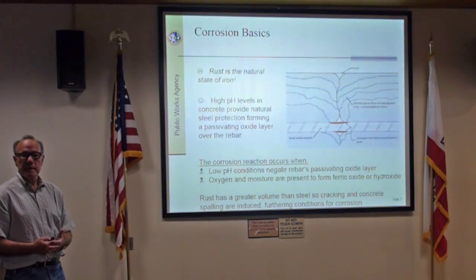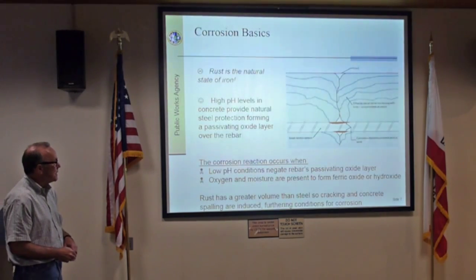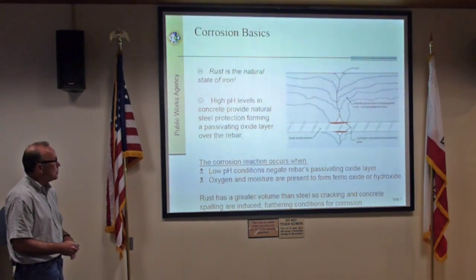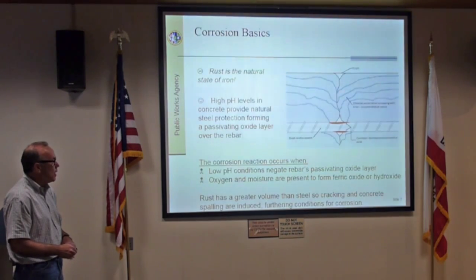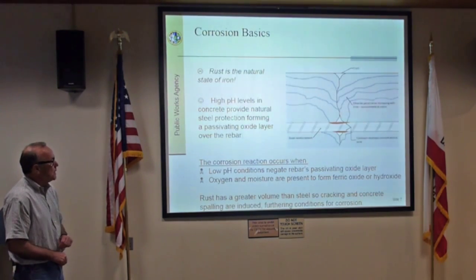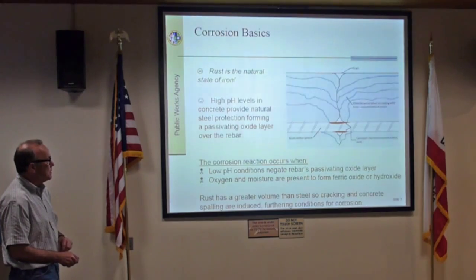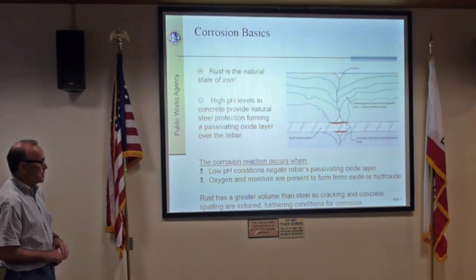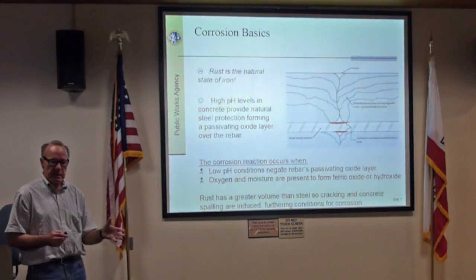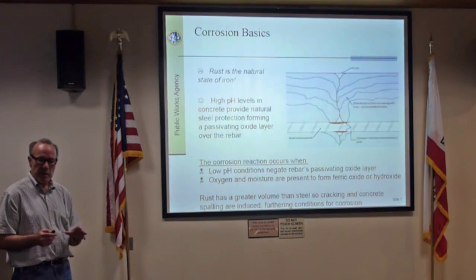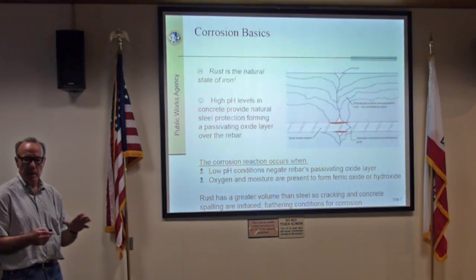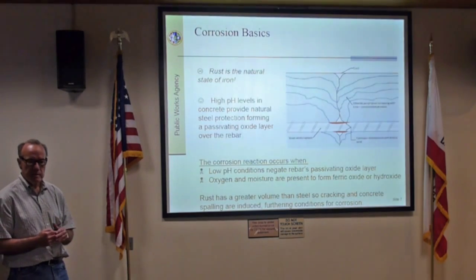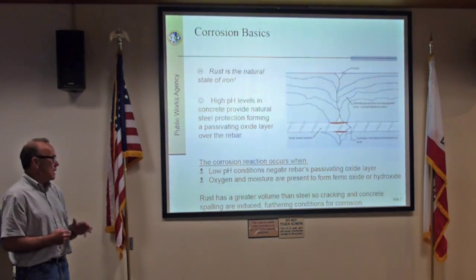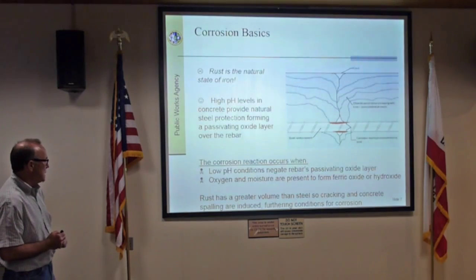But what can depassivate that steel is cracking, or penetration of chlorides, whether through a crack, or water and oxygen, or just over time as they begin to seep in through the concrete, you can eventually depassivate and form a corrosion cell. And there are different types of corrosion, we call macrocell corrosion and microcell, and one of the forms that we've had here is microcell, and it's very, very tough to detect, and we'll explain that.